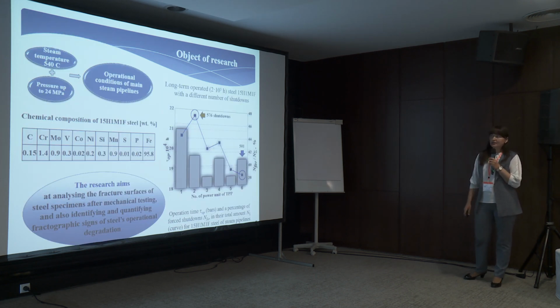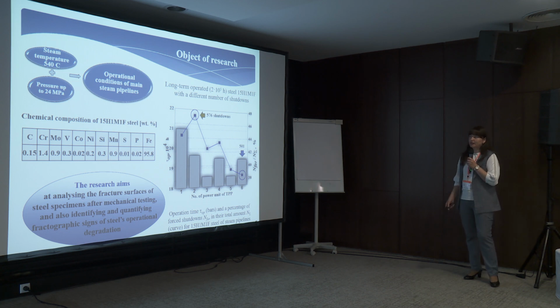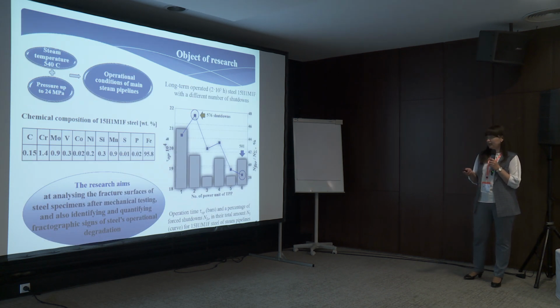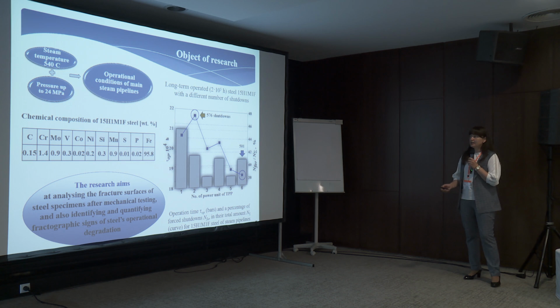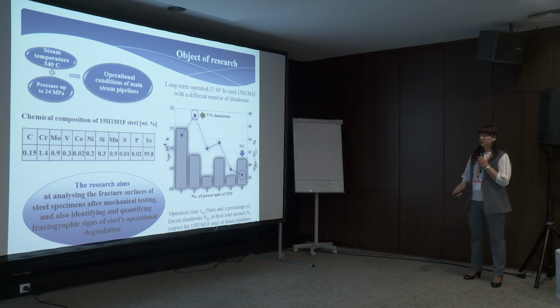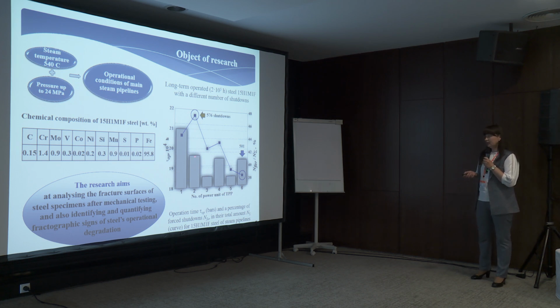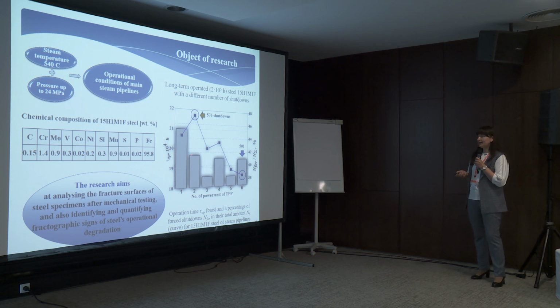The main steam pipelines are operated under temperature 540 degrees Celsius and pressure up to 24 megapascal. In this work, we investigated long-term operated heat-resistant steels. The chemical composition of the steels is presented in the table. The metal from two power units was selected with similar operation time, but different number of shutdowns.